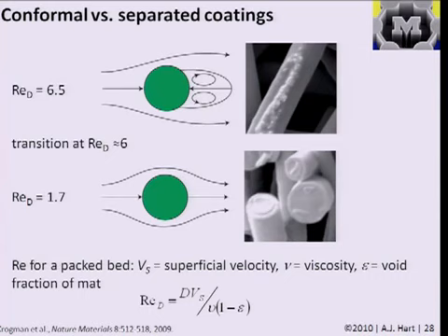But basically, the Reynolds number is proportional to the diameter of the fiber and the free stream velocity of the fluid. And so if they sprayed with a velocity that was too high, there was flow separation around the cross-section of the fiber, and you can qualitatively relate this to the fact that flow did not reach these areas of the fiber on the back, and indeed formed just this bead because of the separation flow recirculating and hitting the back surface. But if they did the deposition with a slower velocity and a lower Reynolds number, the flow did not separate off the fiber, and it deposited relatively conformally around the surface. And these are the conditions, these lower velocity conditions or lower spray flow rate, that resulted in conformal coating of the fibers like so. And this is pretty cool because it happens even though the fibers are fairly well packed.